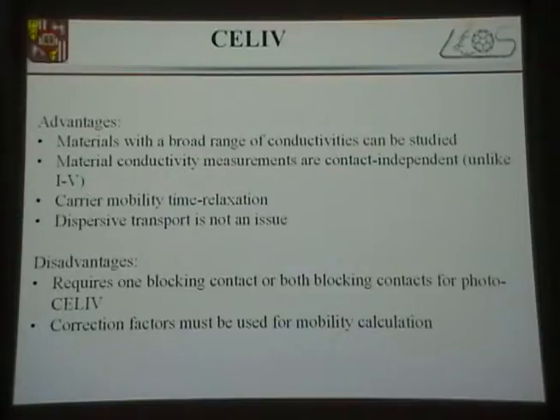And CELIV is just, of course, that's the first thing, that you can study films with a broad range of conductivities. This is very nice because you can study the material conductivity, the film conductivity, which is contact independent. If you measure the current voltage characteristics, the contact might influence your measurement, therefore you're not sure. But in this case, as soon as you have, as a disadvantage, I highlight one blocking electrode, you stop the injection from the electrode, so you extract whatever you have inside, I will talk about it in a second, and you can measure very nicely the film conductivity.